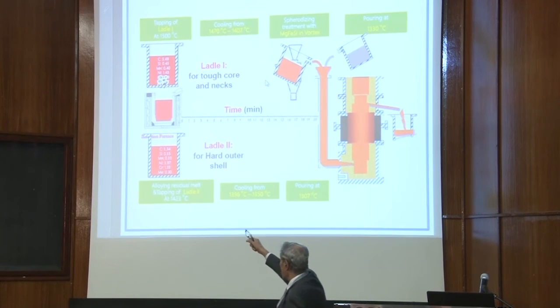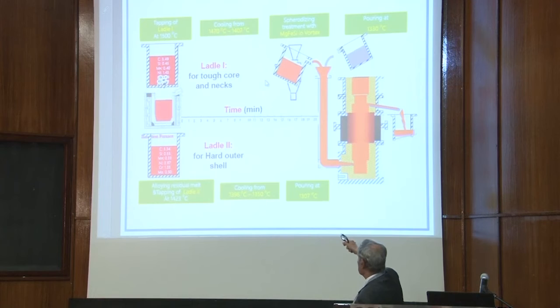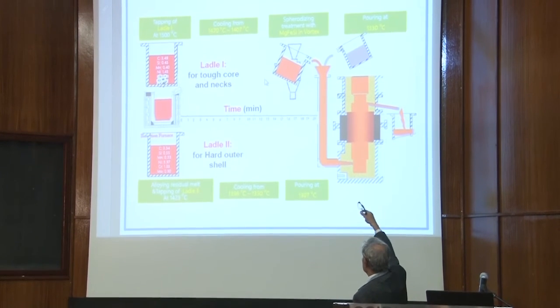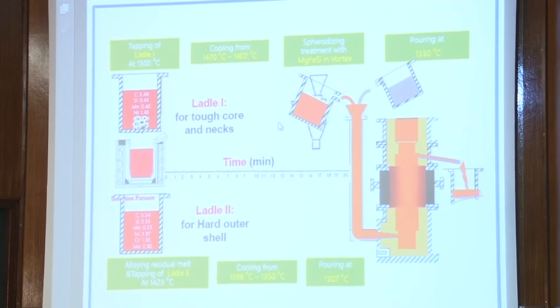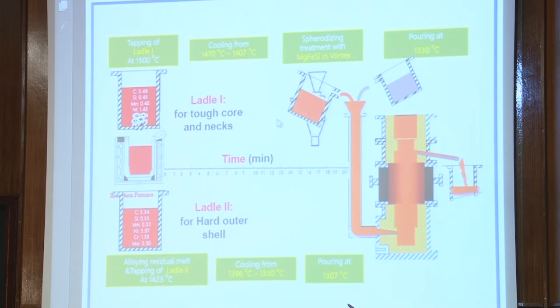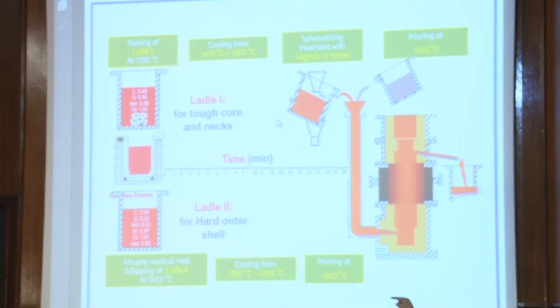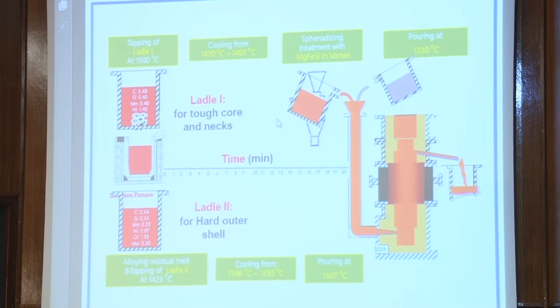Then we took the hard metal, and it was cooled to 1307, and then we poured it in the mold and left it for 3-4 minutes to form the outer shell, the chilled shell. At the same time, we took the low alloyed iron, treated it with the vortex process to form spheroidal graphite ductile iron, and poured it to form the second layer, the core of the roll. It should have been explained by animation, but unfortunately it doesn't work here. Of course, if you have any questions, or any interest in this technology, we can discuss it after the lecture.